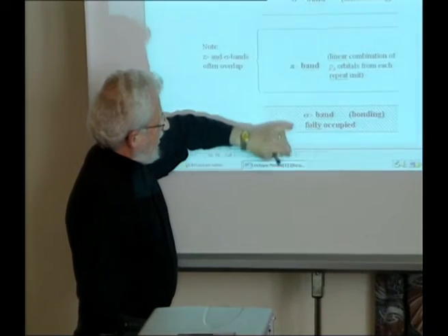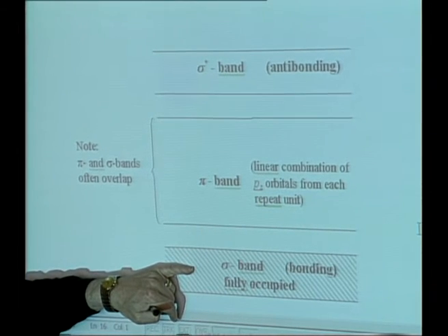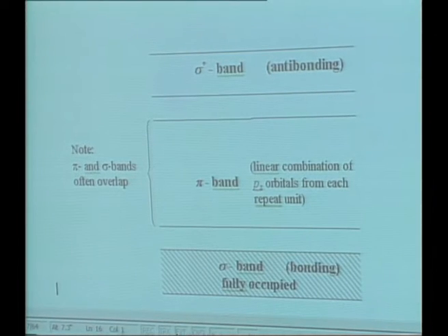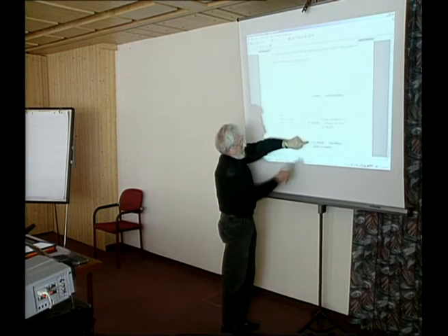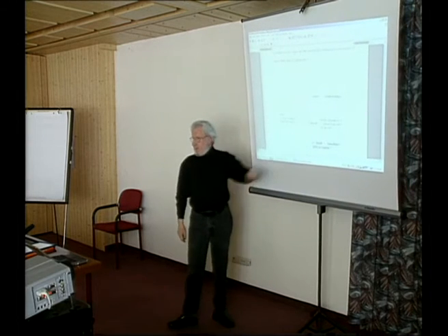the material itself is stable. Why is that? That's because photoexcitations in this structure do not break up the fundamental sigma bonds that are holding the polymer together. If you just have a polyethylene-like structure, make it out of whatever you want. You can make silicones where you photoexcite from the sigma to the sigma star band. This hole makes it a photoresist.